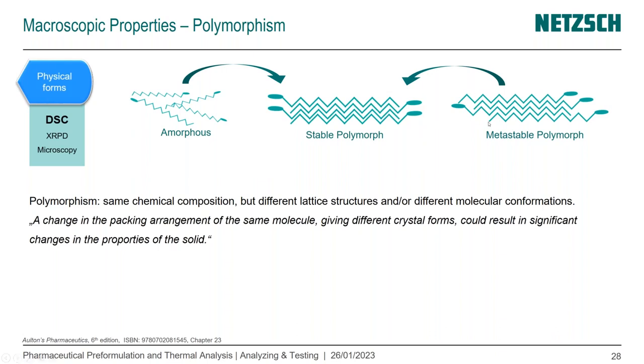If we have the physical-chemical characteristics from metastable polymorphs that are more interesting for the formulation, we can use that. There is no problem. But we have to be sure that this change on the structure will take place after the shelf life of the product. If it happens before, we will change the bioavailability of our material, and it will change the therapeutic efficiency of it.